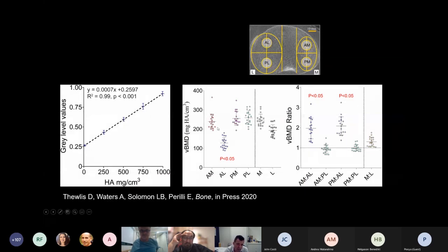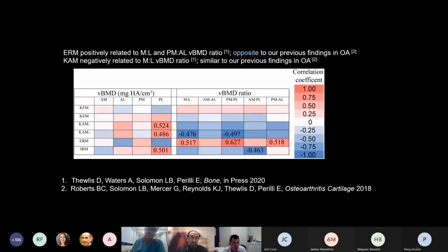We find that anteromedially, posteromedially, and posterolaterally we have a sort of uniform distribution of bone, but anterolaterally it is lower. That is similar to what we found in OA, but the difference is that posterolaterally we have more bone in normals. So something is telling us that something might be shifting with the pathology. And also here, the medial to lateral ratios are similar, but in part different to what we have in controls. And how does this go in OA? How does this go with the gait analysis? Well, that's interesting.